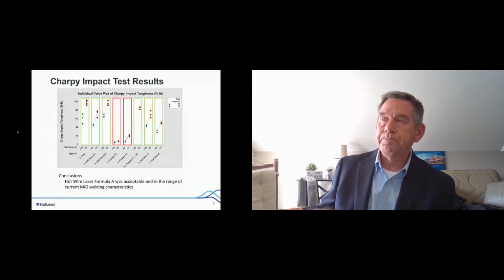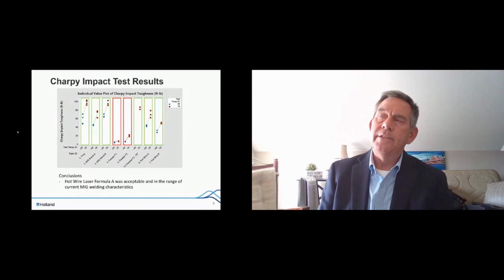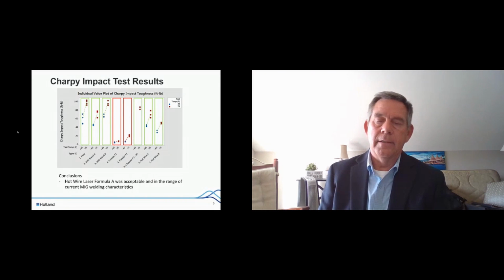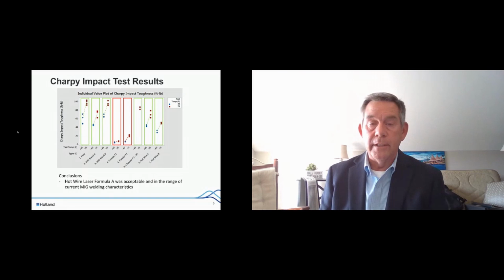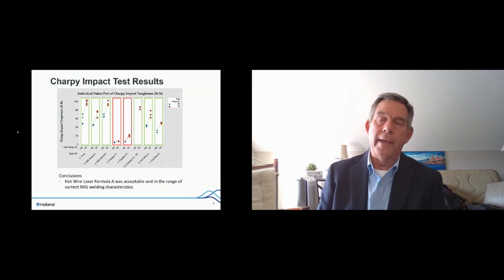The first one is the Charpy impact test. This is a measure of the brittleness of the material, and certainly in this application, we do not want to have a very brittle material. On the far left are the results. It's done typically both with a cold and a hot temperature. So you see the blue dots are the cold results, and the red dots are the hot results of the test.